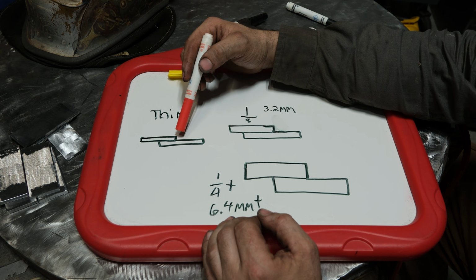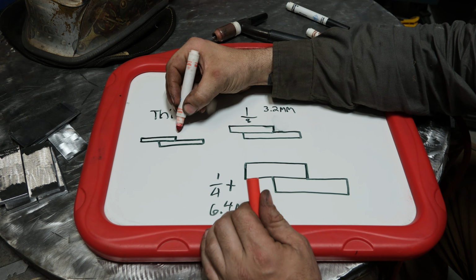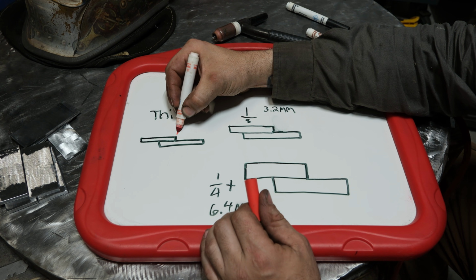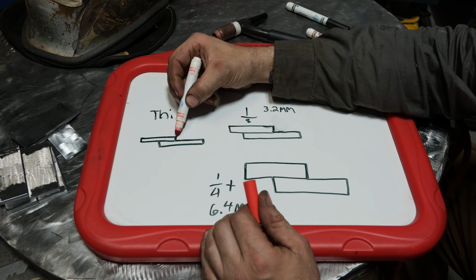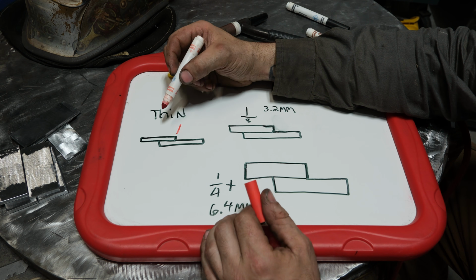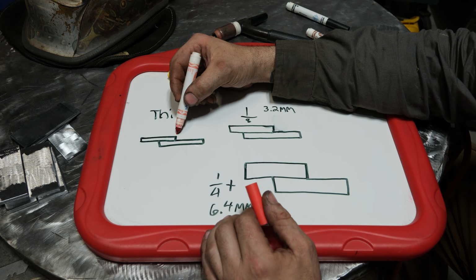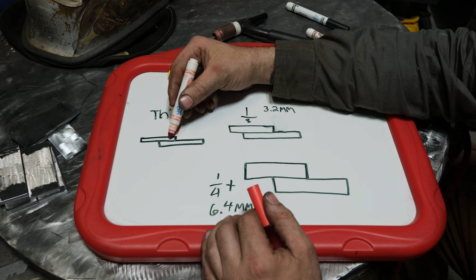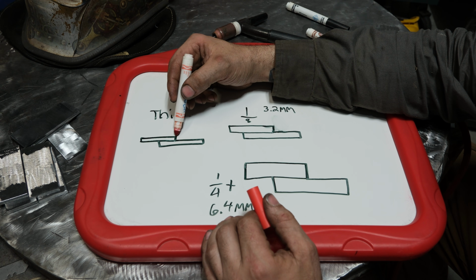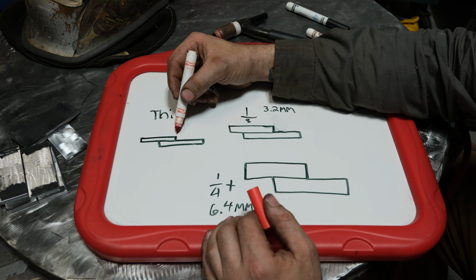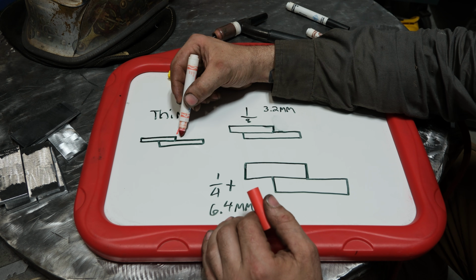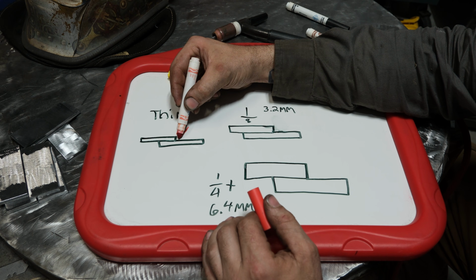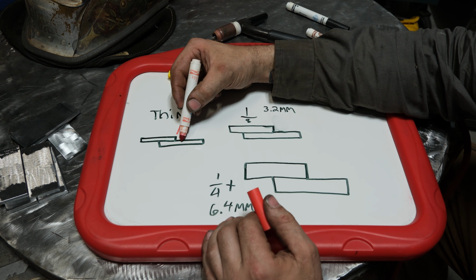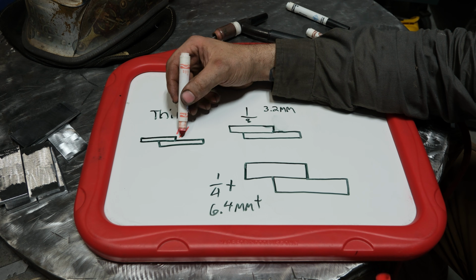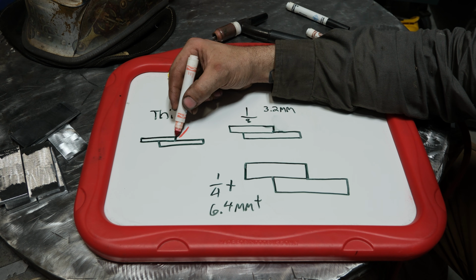On super thin material, it's very common to have your tungsten more or less come in at this angle, and you're nipping the top edge and melting it down into the base material, especially if you're just doing a fusion weld and you're not using filler. And because the material is so thin, you can get away with this, and that works just fine. What you're going to find is on super thin, if your tungsten angle's out here and you're trying to melt this down, you'll probably poke a hole right through this, and you don't want that. So on super thin, you want to aim for this top edge of the plate and melt it down.